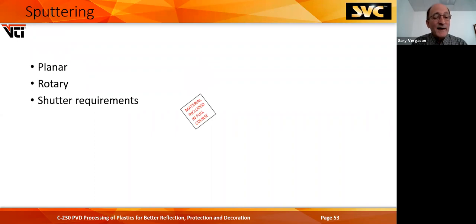In sputtering, you got planar, rotary, and in some processes, you need to put a shutter over the sputter source. So first, when you turn it on, you're sputtering onto the shutter, not onto the substrate. So when your first few ions are arriving on the substrate, they're absolutely clean, and they're not contaminated from, say, something like the vent gas coming back into the chamber.